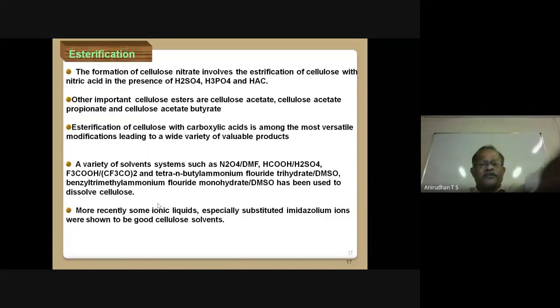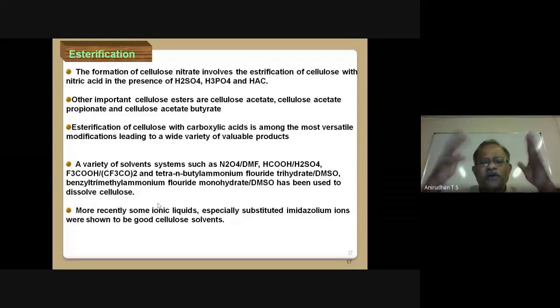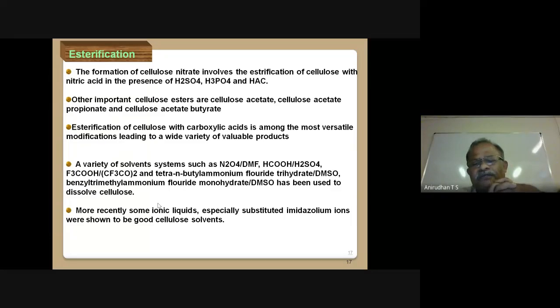And one of the most important problems that we face during the preparation is the solubility of this cellulose. So we utilize a variety of solvents such as N2O4, DMF, formic acid, sulfuric acid. So combinations of different types of solvents, of course, are utilized during the preparation of the materials. Different solvents may affect your product, and properties may be changed. So you select accordingly the suitable solvent for solubilizing your cellulose, so that your product may have entirely different properties. And this is one of the important things that chemists consider. More recently, we have ionic liquids as solvents, especially imidazolium ions, which are utilized as cellulose solvents.